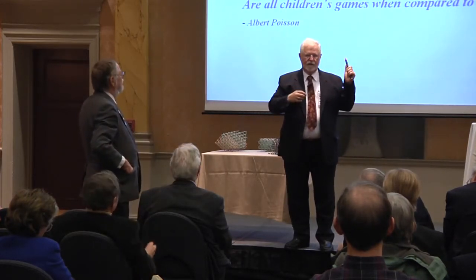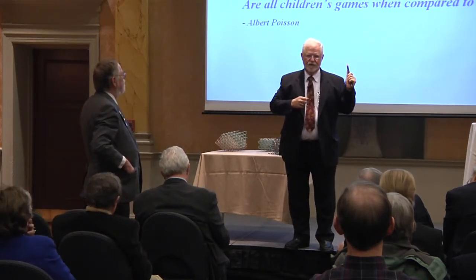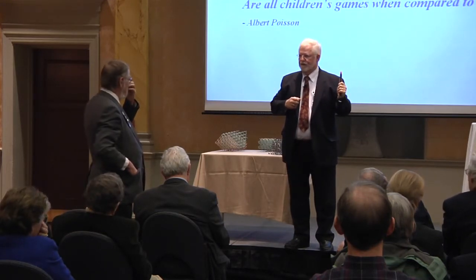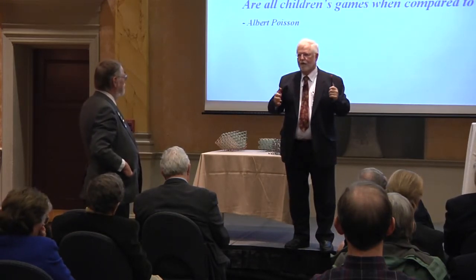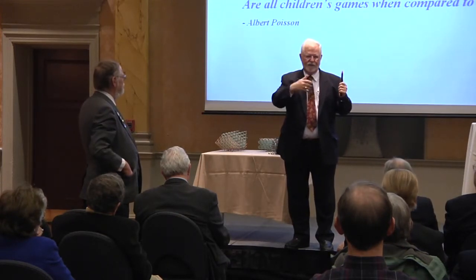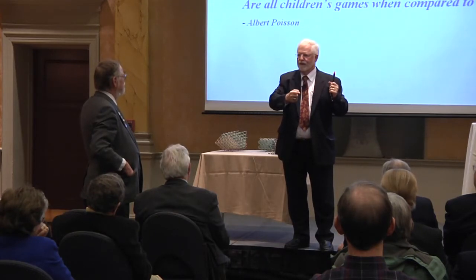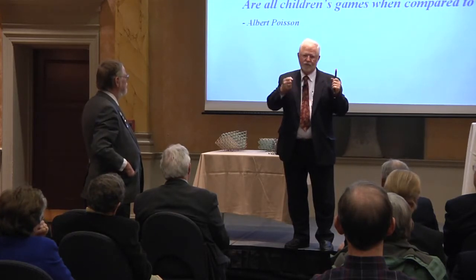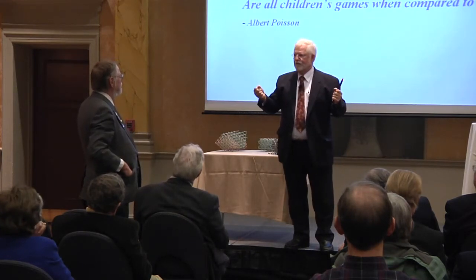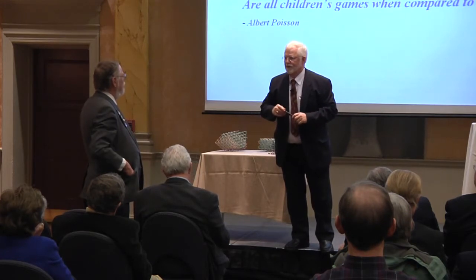Well, one of the things I hope I've convinced you of is the role of atomic hydrogen and how much atomic hydrogen I have to make to grow diamond. I have on the order of probably 10 to the 6th, 10 to the 7th atomic hydrogen atoms that I have to make to get one carbon to grow into the diamond lattice. That is not very energy efficient, because to make that atomic hydrogen I have to dissociate molecular hydrogen. So the answer is no, I don't think this would ever be a good way of sequestering carbon.